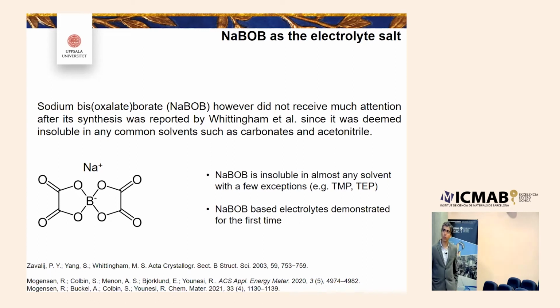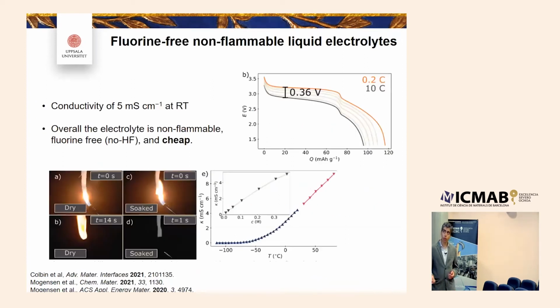So we've been working on phosphate-based solvents, TMP and TEP, together with BOB, and we show that this electrolyte can actually be used for sodium-ion batteries. It provides relatively high, or acceptable, conductivity of 5 millisiemens per centimeter at room temperature. No HF, it's low cost, the synthesis is relatively easy, there's no need for fluorine, and it's non-flammable. Excellent. So this is the main electrolyte we have been focusing on in the last few years.